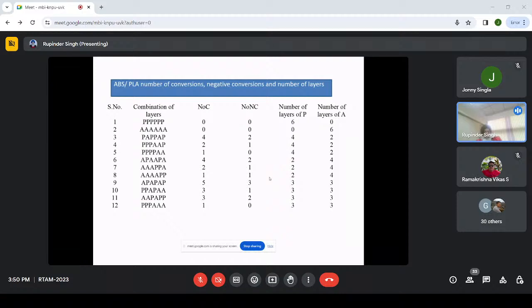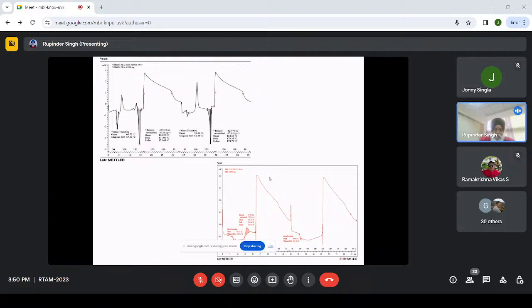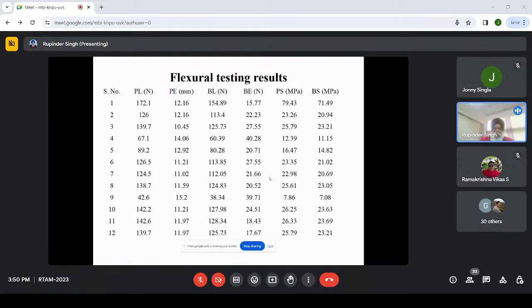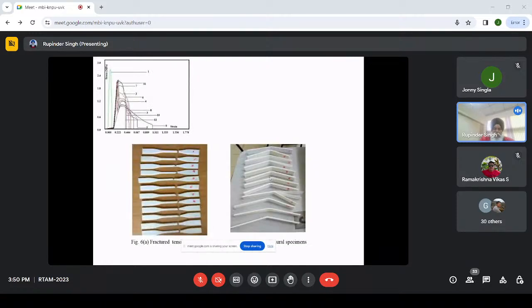What we observed, for the strength to be maximum, number of negative conversion should be minimum, followed by number of conversion, followed by number of P's, and followed by number of A. We registered this as our thumb rule, and this was printed, and we tried to correlate with its thermal properties and other mechanical properties like the flexural strength. So we observed a particular trend for these types of smart materials. In other words, if you want to tune the property, specifically the metastructure part also, you can do that and play with the different types of properties.